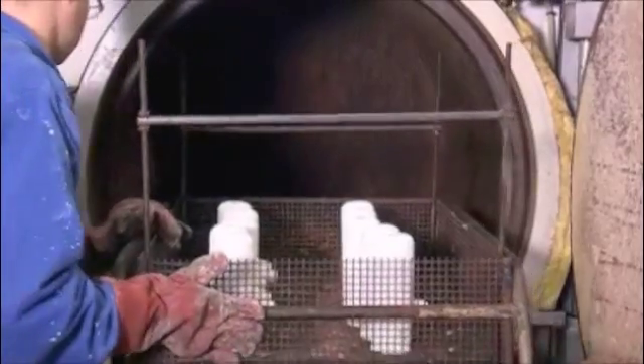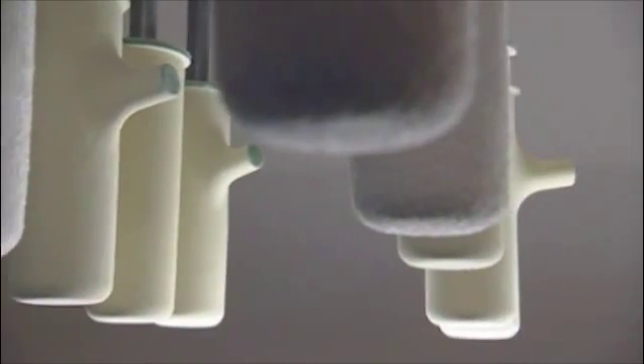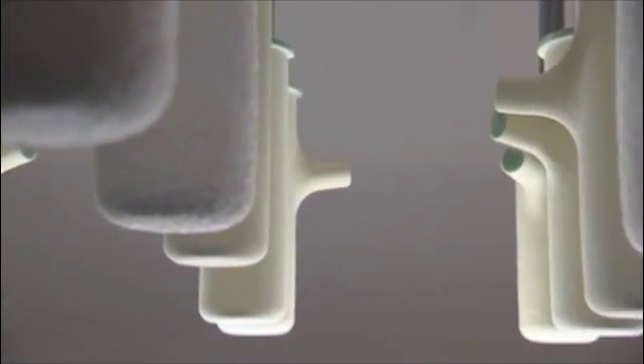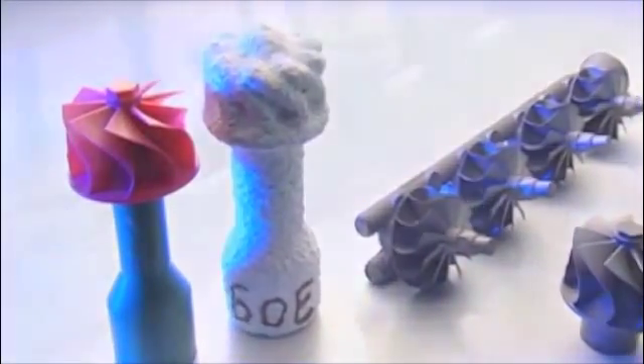When dry, high steam pressure is applied to remove the wax from the mould shells, which are then sintered in a furnace at high temperature. The all-important expertise is the ceramic mould shell, especially developed at AXESS for gamma-titanium aluminide.